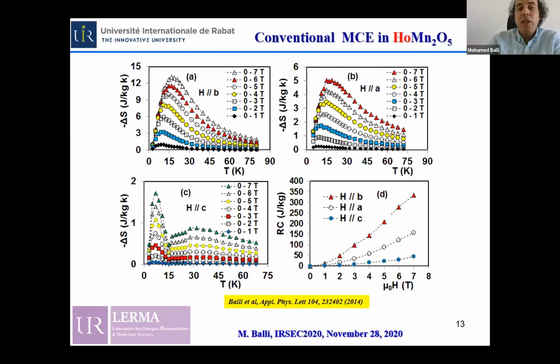This giant magnetocaloric effect is located over the temperature range around 10 Kelvin, which is the helium range, while along the hard axis corresponding to the C direction, this material, as expected, involves moderate magnetocaloric effect in terms of the entropy change.